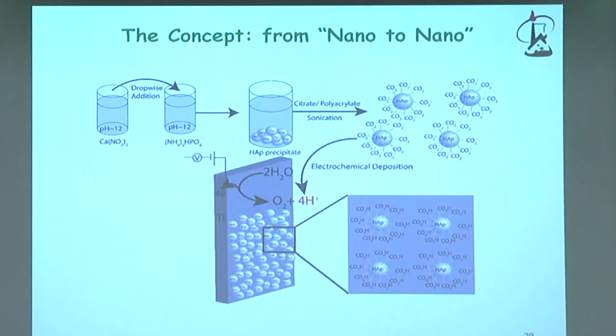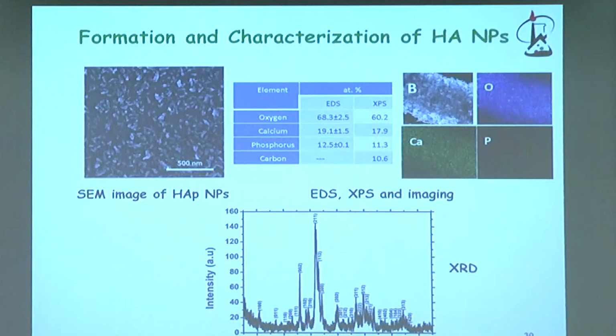We stabilize them with different carboxylic acids, such as polyacrylic acid or even citric acid. And then, in this case, we apply positive potential, which generates protons on the electrode surface, and because of that, we partially neutralize the negative charge of the carboxylic acid, and we drive their spontaneous deposition. And indeed, it works very well.